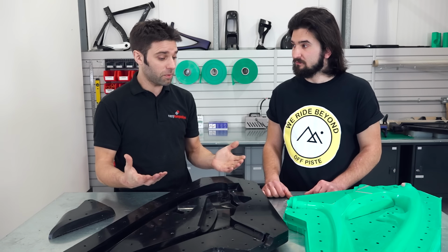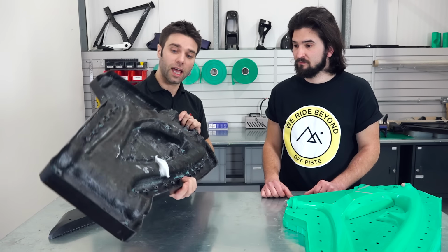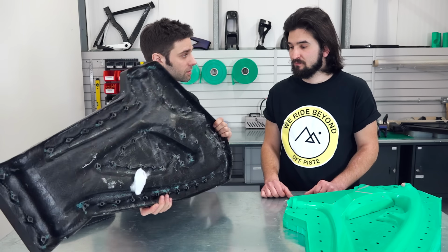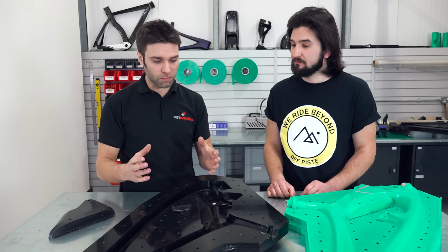The actual layup of this itself, Vlad, how many plies of material do you have in this mould? Well, it's pretty simple. It's one layer of the surface ply, and then we have another 5 backing layers, which are high weight. Yeah, and so that builds up the main bulk of the mould. This builds up and bulks it up and gives the strength to the mould.